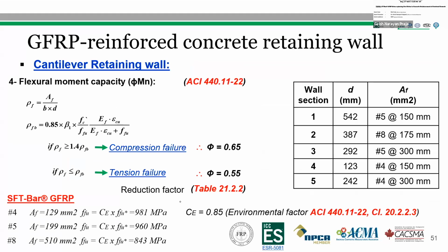Coming to the design of the GFRP reinforced concrete retaining wall, the reinforcement ratio is calculated using the area of the FRP bar provided for each section, considering the same area as the steel bar. For the calculation of the reinforcement ratio, d is the effective depth as given in this table for each of the sections. Now we will only consider section 1 for the design, and the design for the rest of the sections will be the same. For the design, we have to apply a reduction factor, and in the case of GFRP reinforced concrete, we apply a different reduction factor depending upon tension failure or compression failure. If our reinforcement ratio is greater than or equal to 1.4 times the balanced reinforcement ratio, then it is a compression failure, and our reduction factor is 0.65. For tension failure, the reduction factor is 0.55.